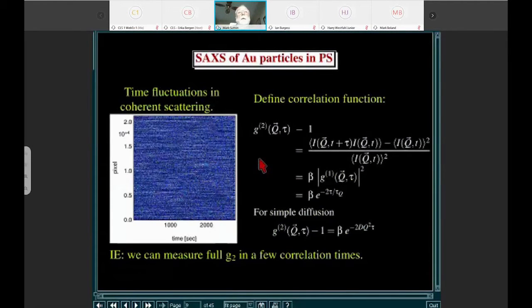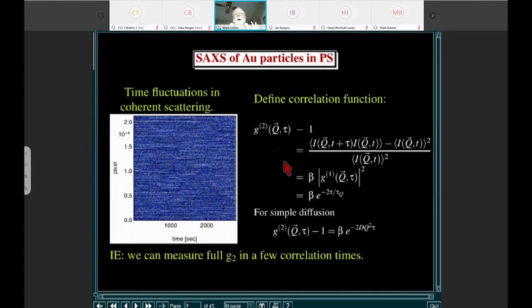Now it turns out that the coherence conditions are much easier to satisfy at small angles than at large angles. But in general, if you have an incoherent diffraction pattern, which is spread over a range of angles, then when you use a coherent beam, that smooth diffraction pattern will be modulated by a speckle pattern. The only issue is, can you measure the diffraction pattern fast enough so that the fluctuations of the particles don't average away the speckle pattern and you get a smooth thing? If it's static enough, you can basically measure the speckle pattern.